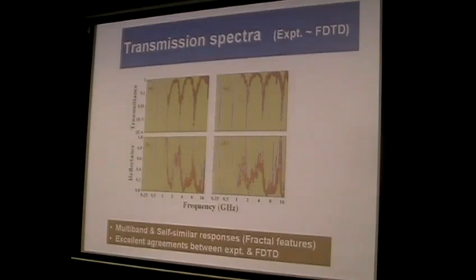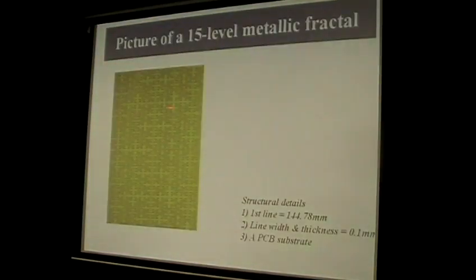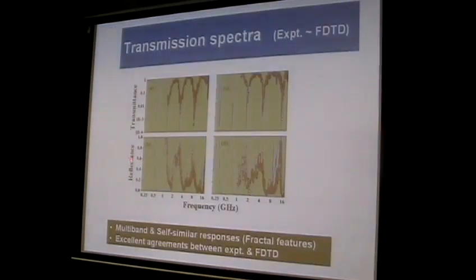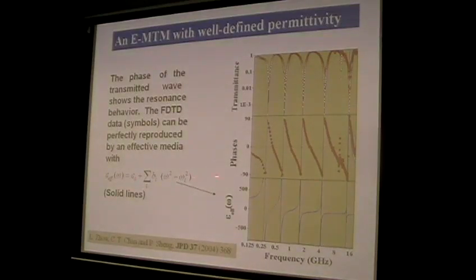So at the frequency that we are interested in, we can homogenize this system as a homogeneous material with a well-defined epsilon and mu. Now that we already have transmission spectra, we then retrieve the effective parameters of this effective plate. And we found that this fractal plate, although it's very complicated, can be homogenized as a homogeneous plate with effective permittivity like this, which is given by a series of electrical resonances. You can find that the dispersion of epsilon effective is given by a series of E resonances here.